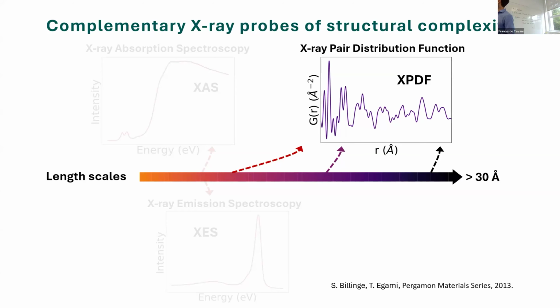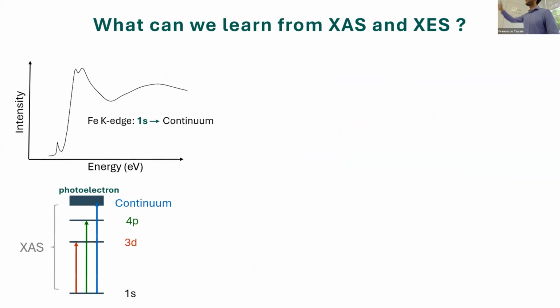But essentially, what the PDF technique does is give you a picture of all the interatomic distances that are persistent in your material across all length scales, from, let's say, 1.5 angstrom to at least 20, 30 angstrom. So this is very powerful. And what can we learn, for example, from XAS and XES, so from X-ray absorption and X-ray emission spectroscopy?